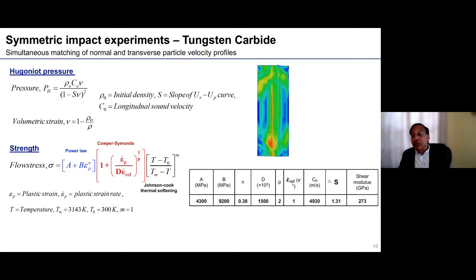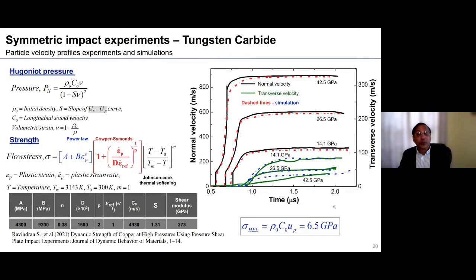So this S is the slope of the Us-Up curve, and this is well known in the literature for tungsten carbide. So now what do we do? We do the numerical simulations until we get the best match. You can see the details of the constants explained in the recent paper just published. So here we see the tungsten carbide, for which I showed you the normal and the transverse response. Now you can see the dashed lines are the simulations. So we can capture extremely well, obviously, the normal response.